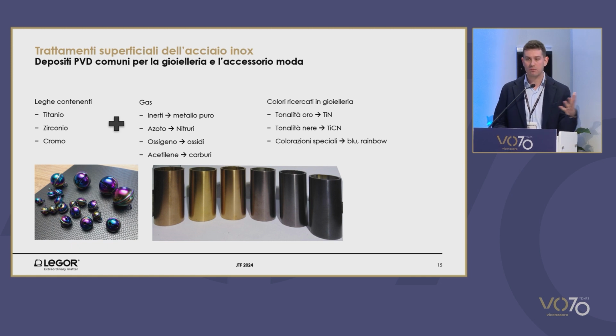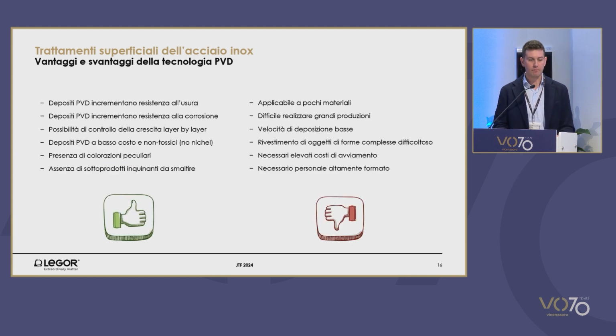Coating by means of PVD includes titanium, zirconium, and chromium, which interacting with inert gas can create the pure metal, or oxides and carbides of the above-mentioned materials can be generated. The colors that are usually resorted to in the jewelry and fashion industries are the ones that simulate gold, and those are obtained by means of deposition of titanium nitrides that look more like 24 karat gold. Titanium carbonitride (TiCN) is often used to obtain other colors different from the ones that you may obtain with other technology. For example, bluish coloring, or the famous rainbow effect that you see at the bottom of the slide on the left.